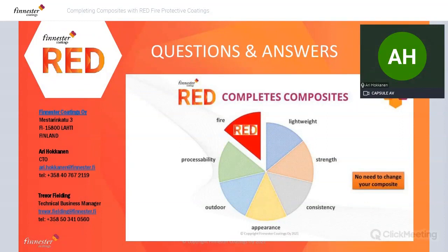So the first question is, which thermoplastics could be used in combination with Red technology? We have quite extensive testing done with polyamides and then PLA. But we don't recommend polyolefins, of course. So PP, PE is out, and that's without any surface treatment. But polyamide is working very nicely. And what else do we have? PMMA, yeah.